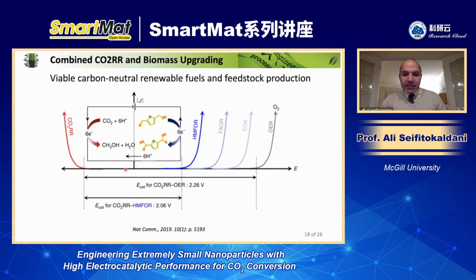So here you see the applied potential for the OER, for the oxygen evolution, is very large. And the product that you generate here is oxygen that you don't really want, because you can produce oxygen through other separation methods much cheaper. So it doesn't really make sense to have this reaction combined with CO2RR if the focus is on the CO2 reduction reaction. But we need the oxidation reaction. Otherwise, the electrochemical system cannot work simply. You need to have both sides, the cathode and the anode.